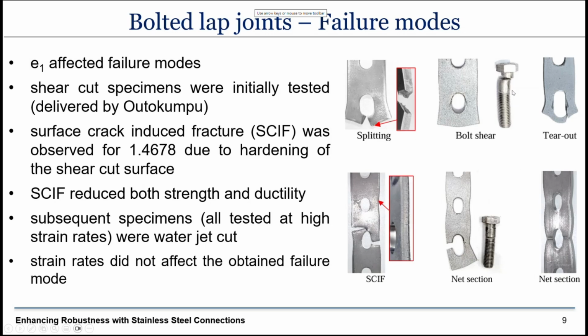These are the typical failure modes we obtained, which we were expecting, like net section fracture, tear out, bolt shear, etc. And this is a failure mode we definitely were not expecting. And we couldn't have obtained that even if we wanted to. So what happened here is that we have fracture, which does not pass through the critical cross-section, the cross-section with the smallest section area. And in fact, the fracture began from the outer sides of the specimen and slowly progressed towards the inner parts of the specimen.